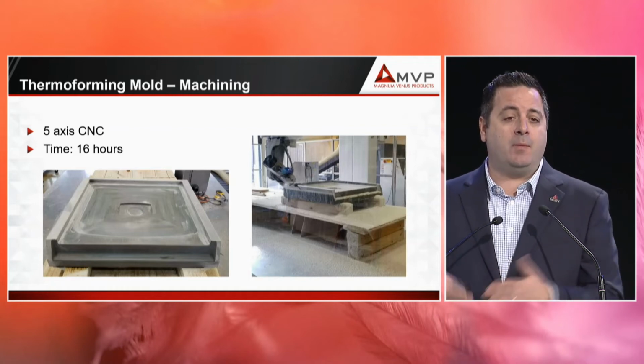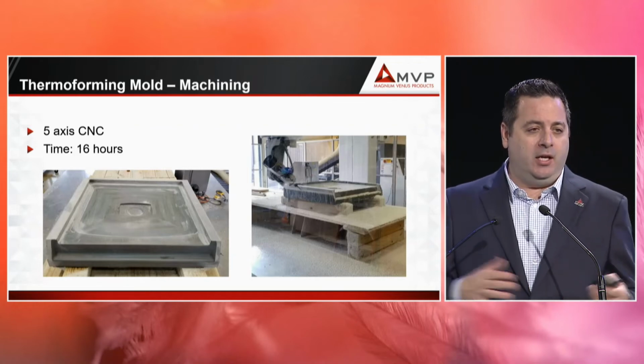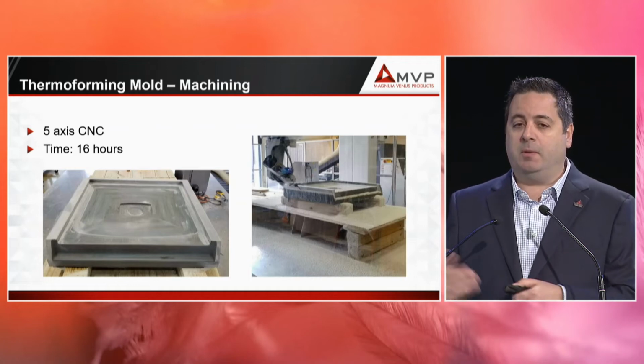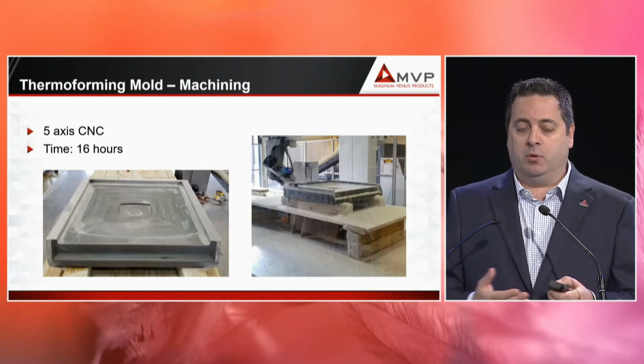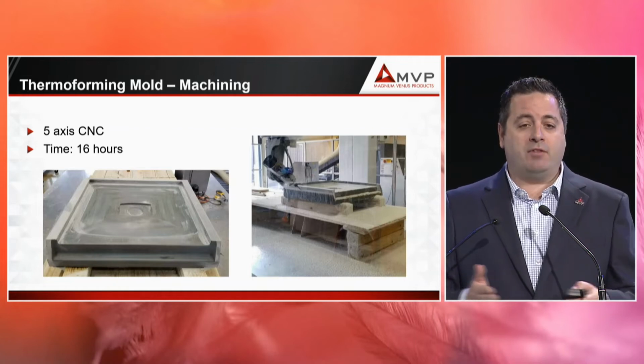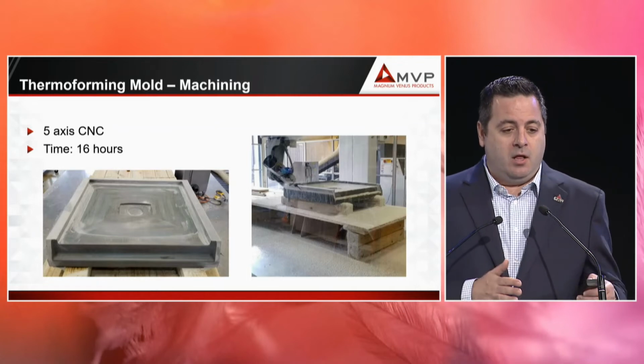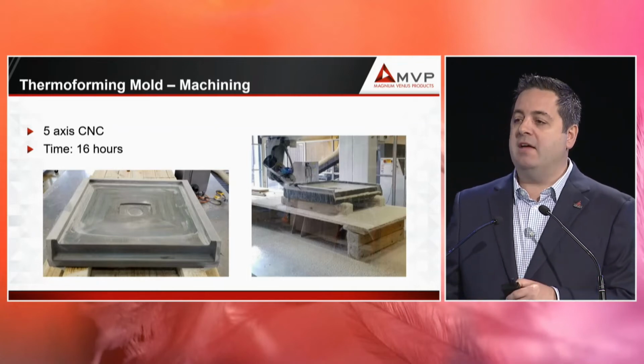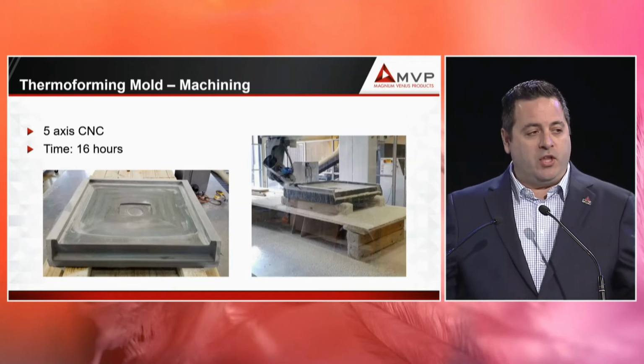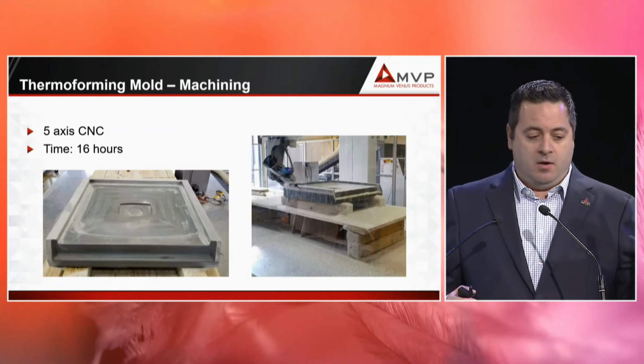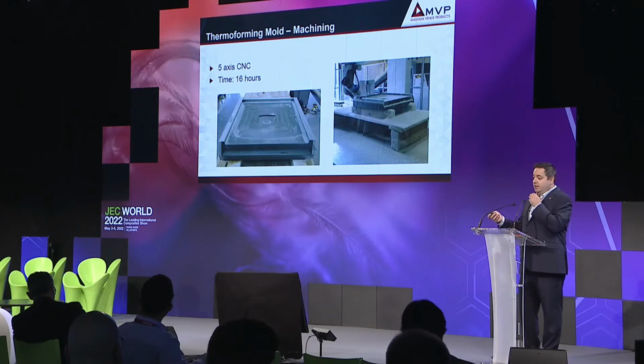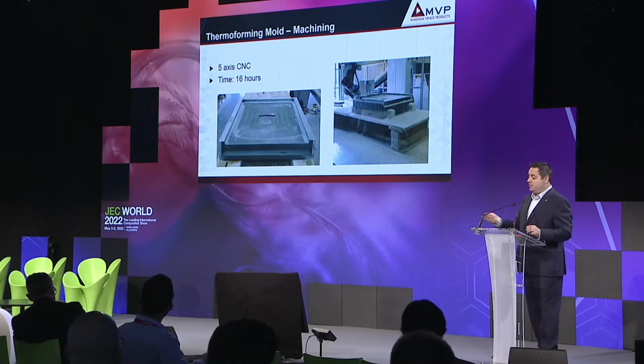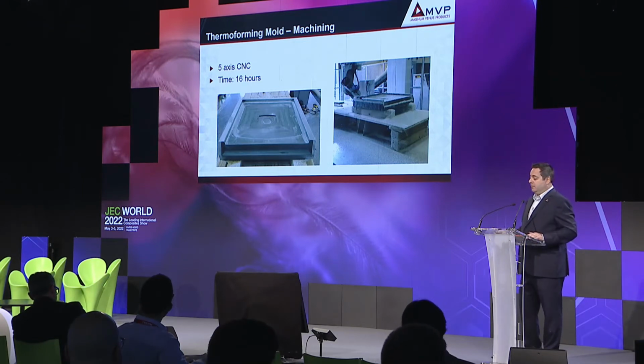On thermoplastics, it's just the opposite, because in many cases, as you're milling, you're heating up whatever material you're milling, and in many cases, the thermoplastic can't withstand that heat. You'll quite literally melt it again, like the butter. And so you have to go much slower on that. And in many cases, milling in a thermoplastic is anywhere from 2 to 5 times what it took to print it. And so if you think about this, the timeline of going from a CAD file or an idea all the way to the end product, there's 9 to 11 steps that you have to take to get there. And printing and milling is just a couple of them, and you can offset those by different efficiencies. And our efficiency is that you can mill faster and it's easy to mill.